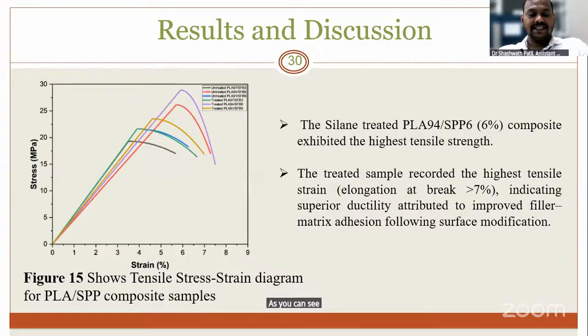As you can see from this stress strain diagram, the Silane treated sample of 6% filler composite shows the highest tensile strength, indicating superior ductility attributed to the improved matrix adhesion following this surface modification. Yes. As you can see from this bar graph, the Silane treated 6% showed the highest tensile strength of 28.8, showing an overall increment of 8.4% compared to the untreated composite, due to the improved interfacial bonding and matrix stiffness.